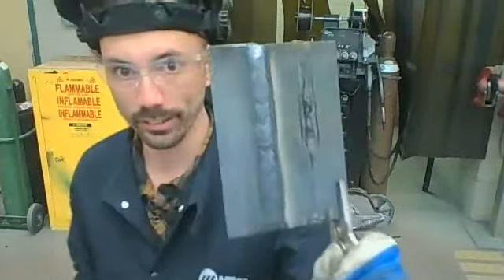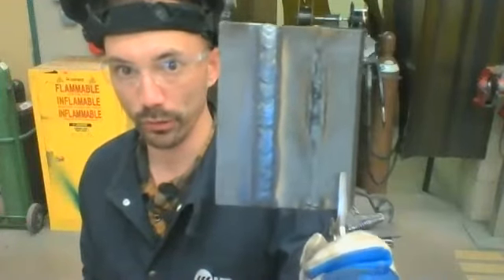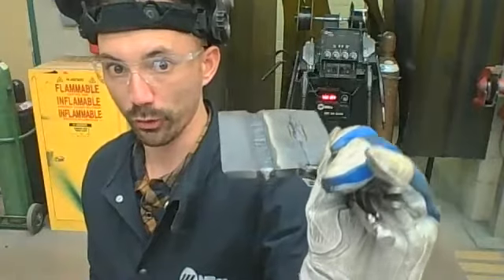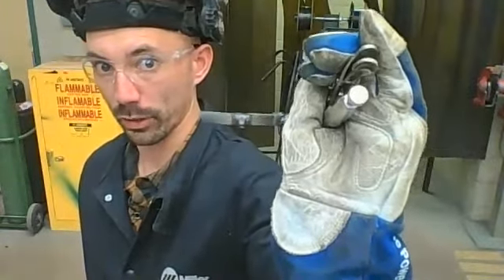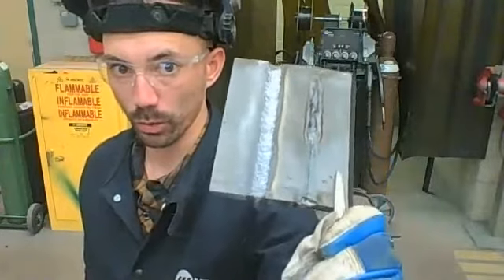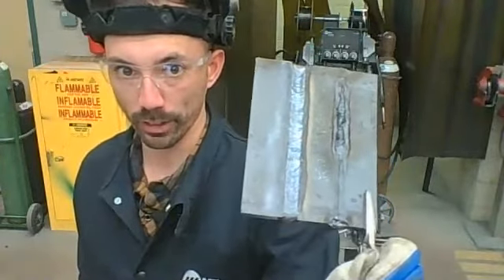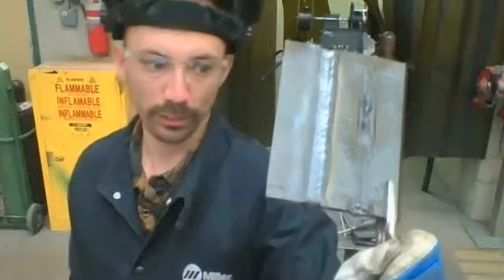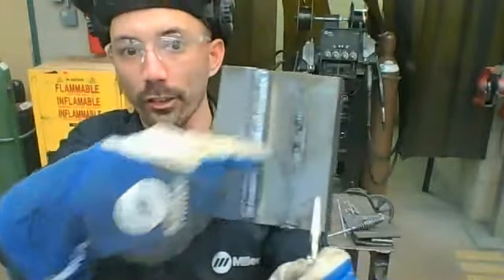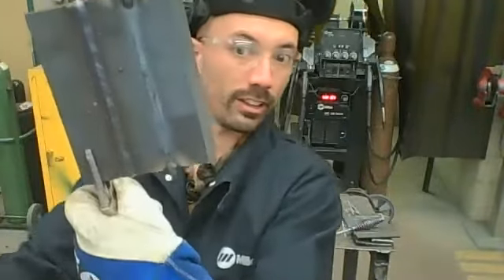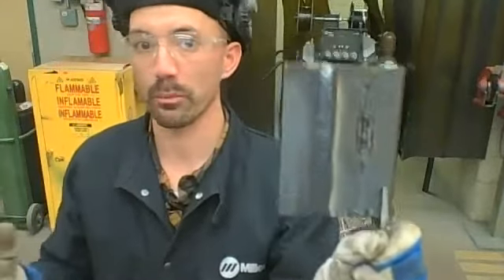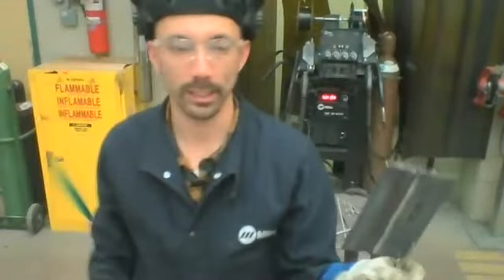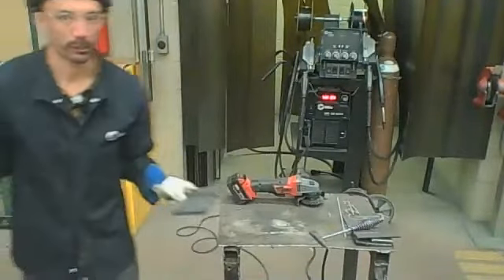So that there looks pretty smooth. It's almost flush the whole way. No major lumps, no major bumps, no holes, no big chunks of spatter in there, not like the first one. So when I was bugging you guys in class about setup is key, right? That ugly gross right there made all the difference on that weld. And this one, if you look at the backside here, I just didn't burn through, and it set me up really nicely for this weld. So that proper fit up and start up is definitely key. I don't think I could show you a better example.